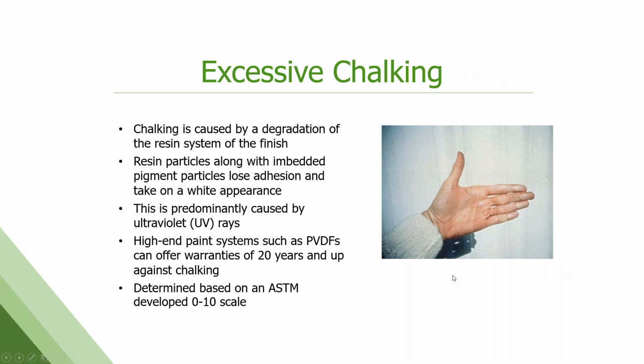So chalking, that's the first one, and this is probably the least understood. Chalking is exactly what it sounds like. It's the surface of the paint becomes white and chalky. It's a degradation of the resin system. The resin particles start to break down, and the pigments that are attached and embedded to those little pieces come off and lose adhesion and create this white powder on the surface, predominantly due to UV exposure.